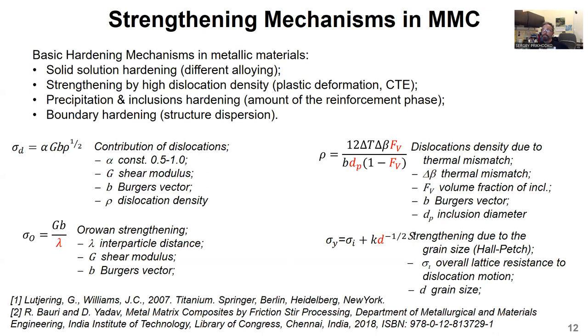Inclusion hardening is related to the dislocations that can bow between hard particles, leaving behind Orowan loops. That gives the Orowan strengthening and involves the interparticle spacing change. This mechanism works on very small dispersed particles. However, when the particles of the second phase are getting bigger, the most likely mechanism turns to dislocation pileup, and the interface boundaries play an important role there. And finally, we have the possibility of structure dispersion related to the grain size change, which can be expected and expressed by the Hall-Petch relationship.